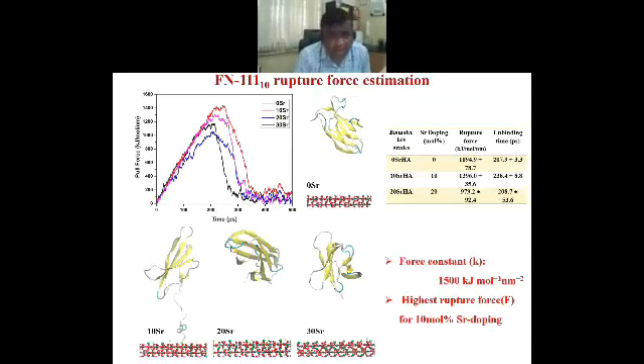Now, what you see in this particular case is fibronectin, the type 3 domain. Here, for the 10 mole percent strontium doped hydroxyapatite, you see that more force is required to pull this fibronectin from the surface. What it essentially means is that the fibronectin proteins are adsorbed on that strontium doped surface much more strongly compared to other strontium doped surfaces. And in this particular case, the force constant is around 1500 kilojoule per mole per nanometer. And the highest rupture force, as I said before, is observed for 10 mole percent strontium doped hydroxyapatite.